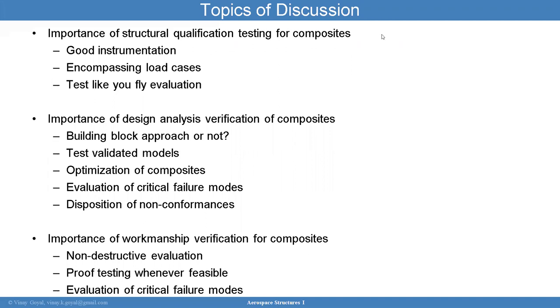As you go through the life cycle, you have to do non-destructive evaluation to make sure you don't have damage occurring at key points in the manufacturing life — from adding features, through acceptance testing, through integration into the primary structure assembly, all the way into fielding. For operations like a composite business jet, you're making sure you don't see any little indentations or dents around the OML, because that could be indicative of impact damage — fiber and matrix delamination, a local weak spot that might be okay for normal flight but could catastrophically rip apart in a critical flight environment.